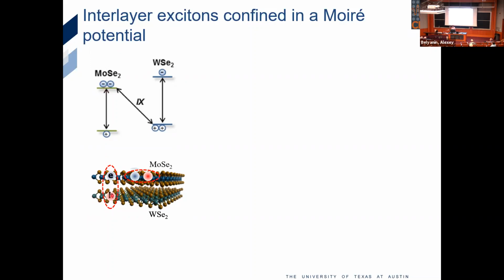So if I have electron in one layer, hole in the other layer, you set up a different kind of exciton that we call an electron hole interlayer exciton, where electron and hole are in different layers. So these excitons have very different properties compared to the intralayer exciton. They absorb less, they live longer, and I'm going to show you how we control their energy and dynamics using the twist control.